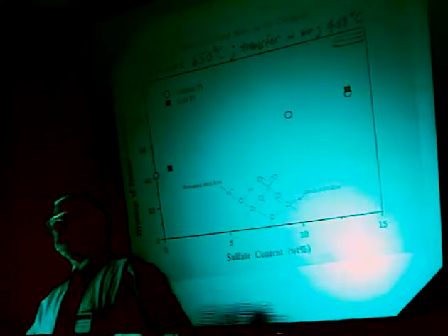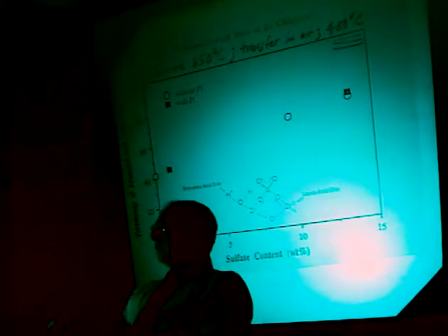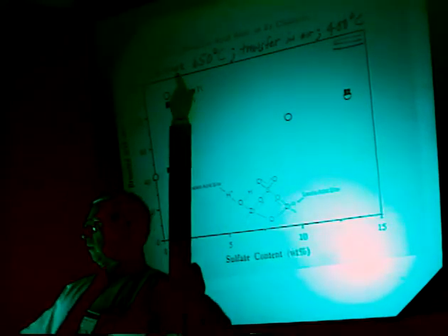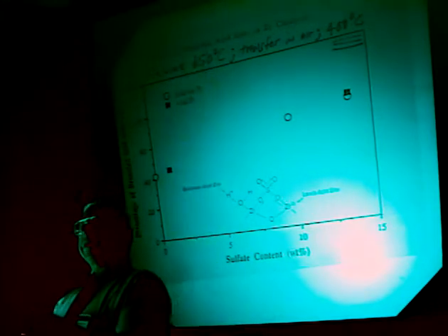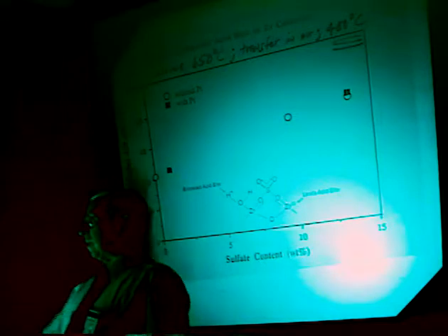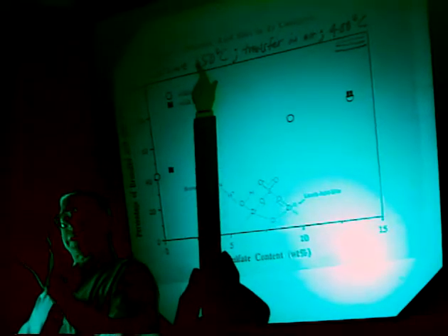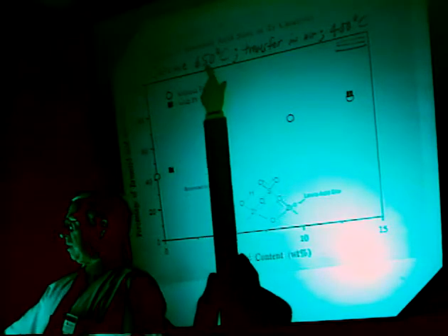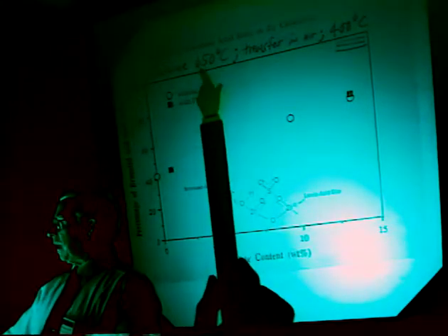Another way to look at the acidity is to use infrared and the pyridine adsorbed. Here I am comparing starting material that has different amounts of sulfate. We have calcined this at 650. Depending on which batch of zirconia we start with, the maximum activity is obtained at a different calcination temperature. This batch gave the maximum activity.